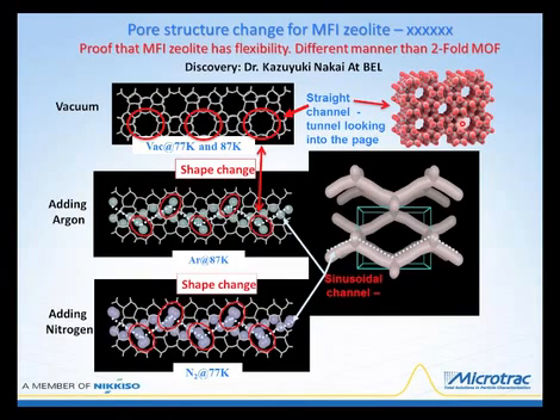Now, originally it had been believed that MFI zeolite did not undergo structural changes at all, and the pore structure did not change during its activity. But Dr. Nakai added argon and did adsorption and structural analysis, and he found that there were actually changes in the pore shape itself. This is not a complete structural change, it's just a change in the pore structure. As a result, instead of having this cylinder or single channel view, now the structure takes on a shape such as this. It has become much more ellipsoidal, represented by the sinusoidal channel, where originally we would be able to look straight down this single channel. Now we have a sinusoidal type channel.